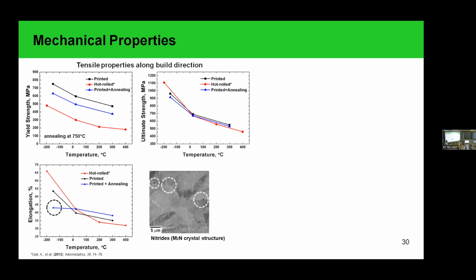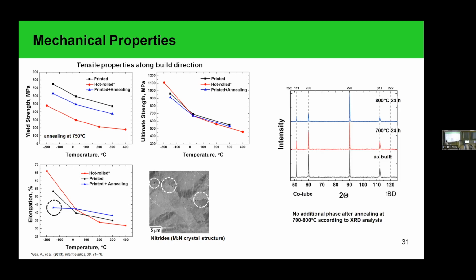The structural analysis demonstrates the formation of small precipitates along the grain boundaries, which were recognized as nitrides. And we assume that it's the main factor contributing to the lower ductility at the cryogenic temperature. But still, according to the X-ray diffraction analysis, we see that the FCC phase is still observed even after longer heat treatment at 800 and 700 degrees Celsius.